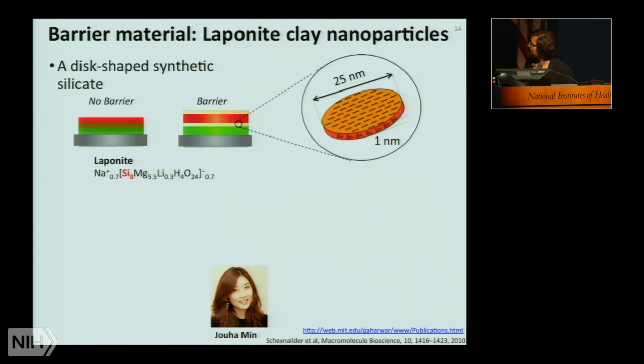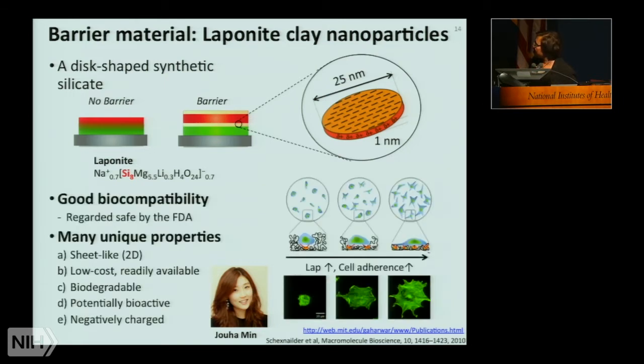This is just a very thin, disc-like nanoclay. They're used for a number of different applications. In our case, we chose this system because it exhibits good biocompatibility. A number of these laponites are generally regarded as safe, and they're very low cost and biodegradable. They are also potentially bioactive. They can actually enhance cell adhesion at surfaces and interfaces. So what we're going to do is use them as a kind of barrier layer in between the 2 drug layers. The question here is, can we get a stagger that we control?